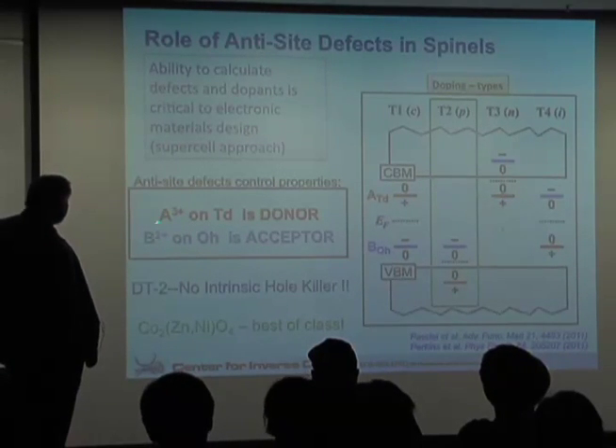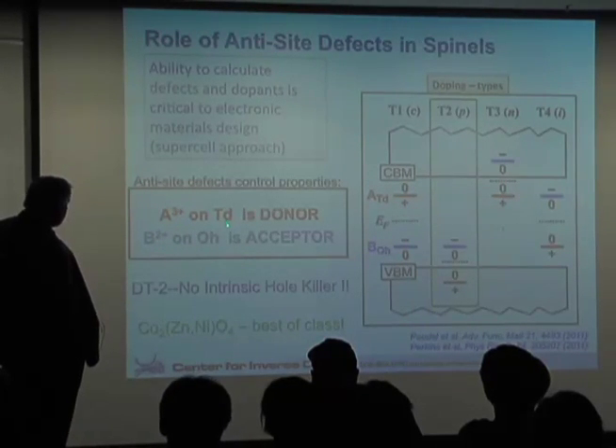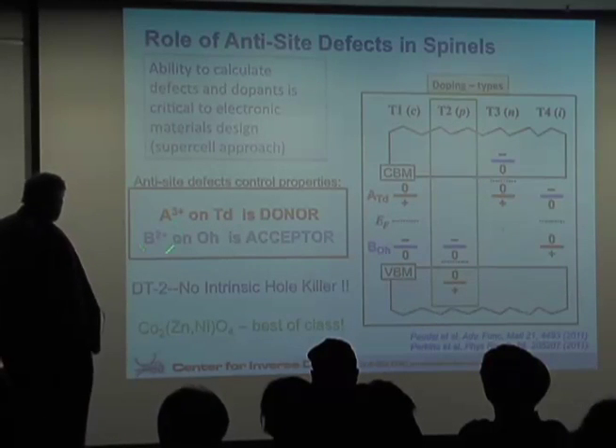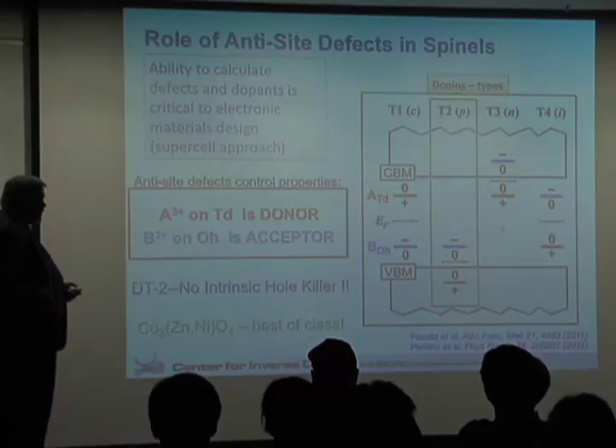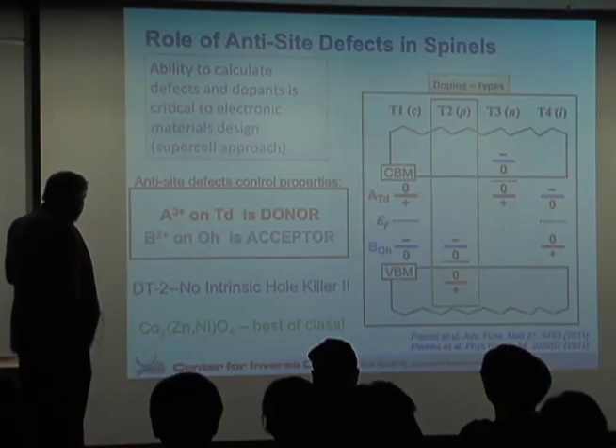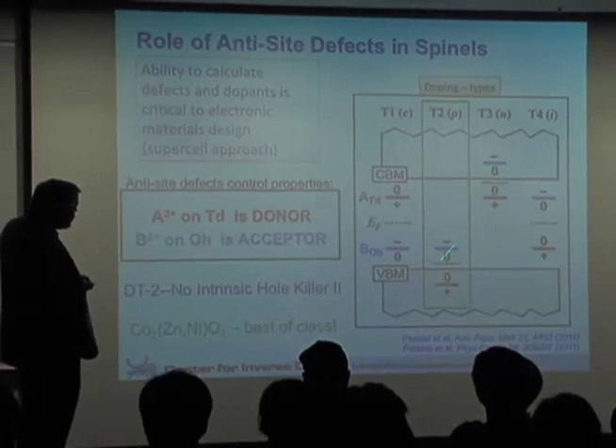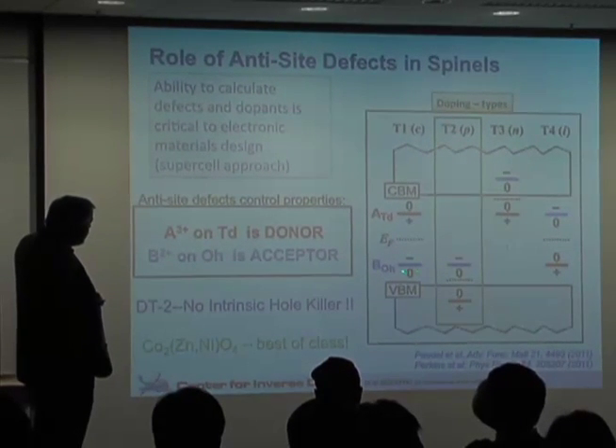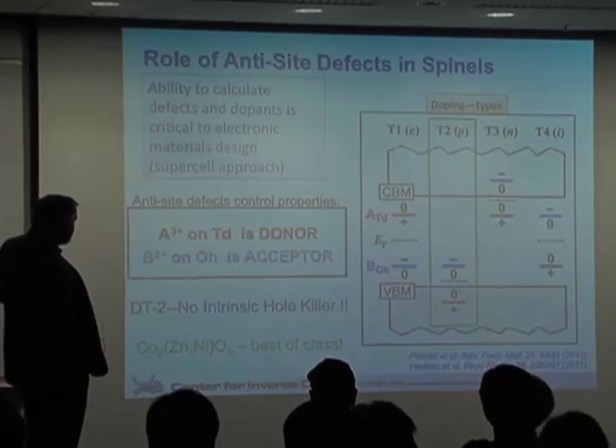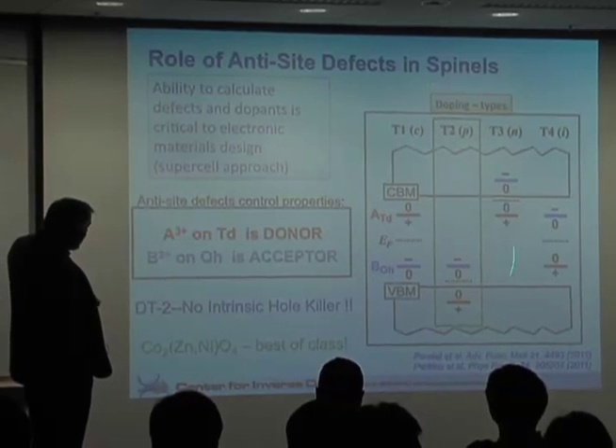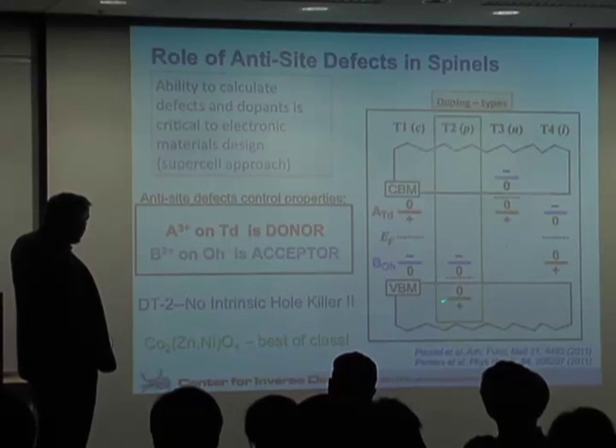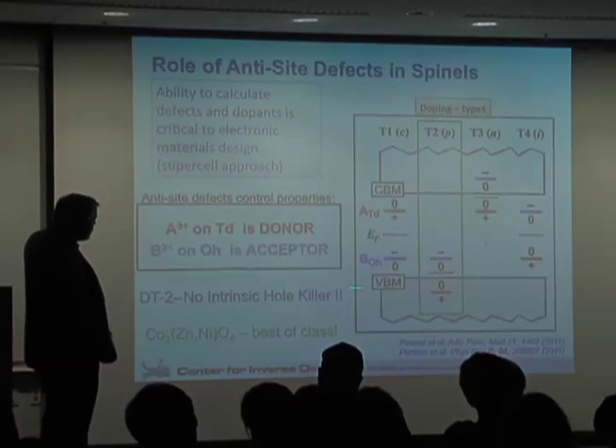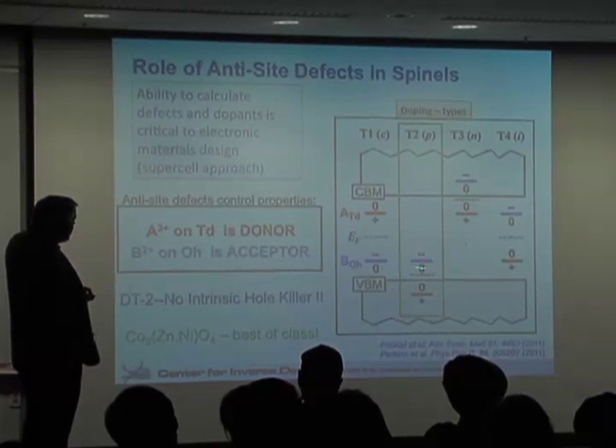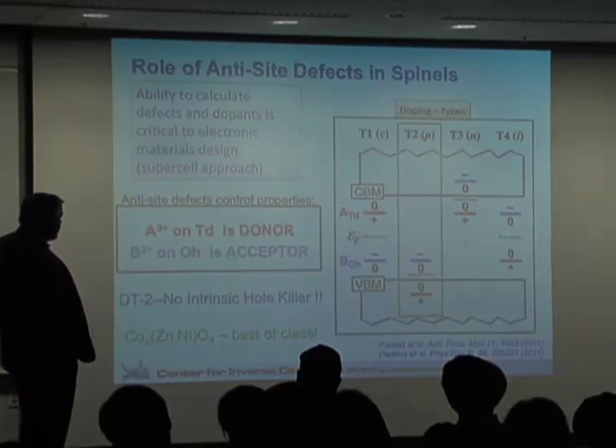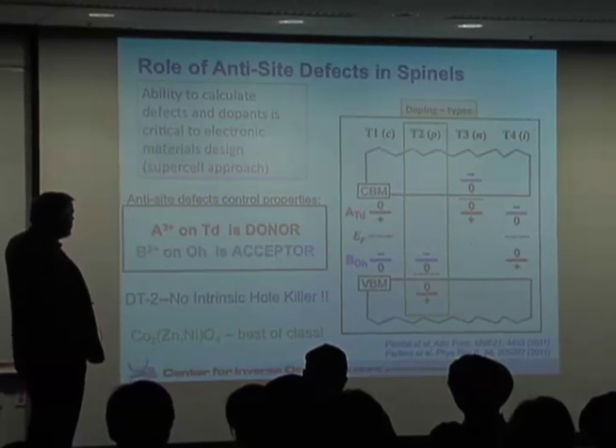We find that the main defects are these, that if you put the 3+ cation on the tetrahedral site, you create a donor. And if you push the 2+ cation on the octahedral site, that's an acceptor. That's actually a hole producer. And in fact, we've then looked at the 4 types of doping mechanisms, which is what is the level of this donor and this acceptor. And it turns out there's one class here that is extremely important. And that is where the donor is actually electrically inactive. It's buried in the valence band. And the acceptor, or the hole producer, is actually out here. And that allows you to get to a p-type system.